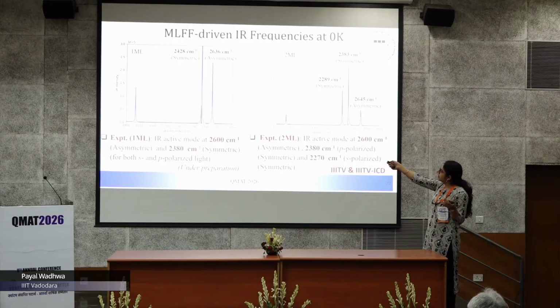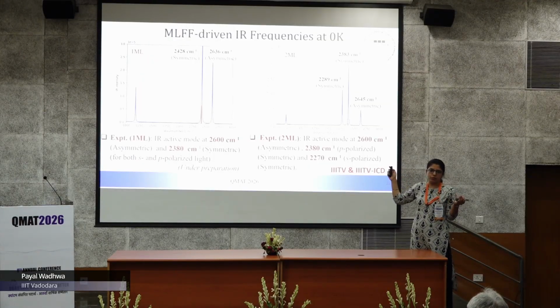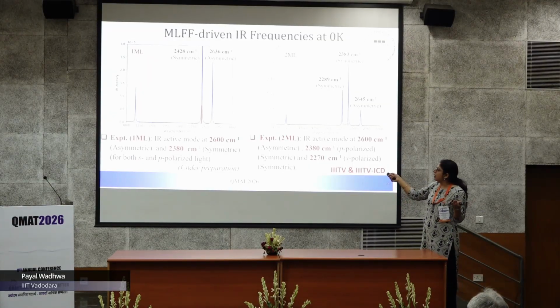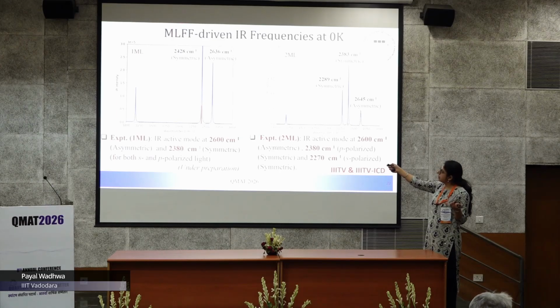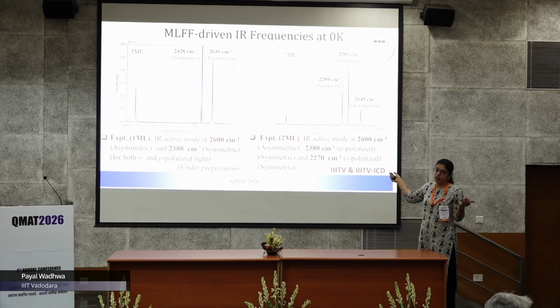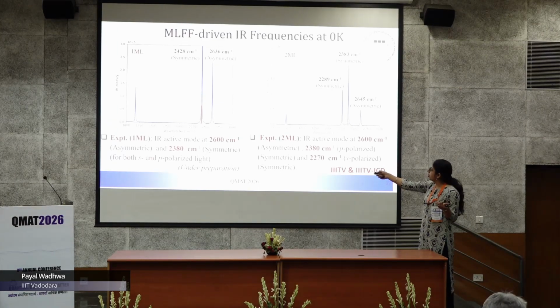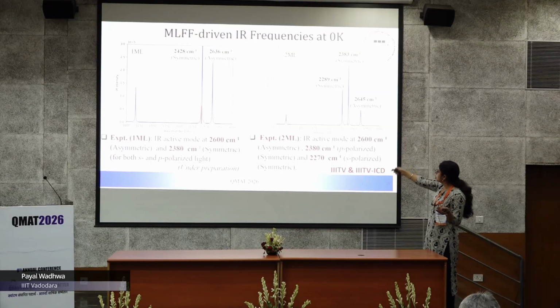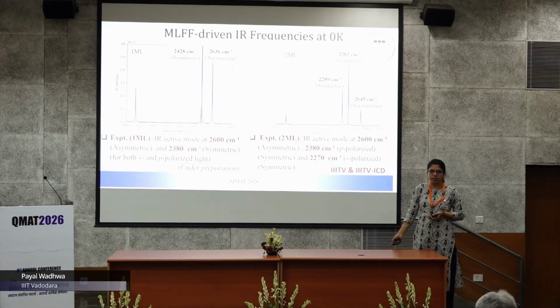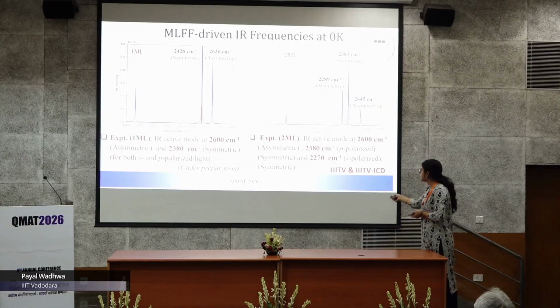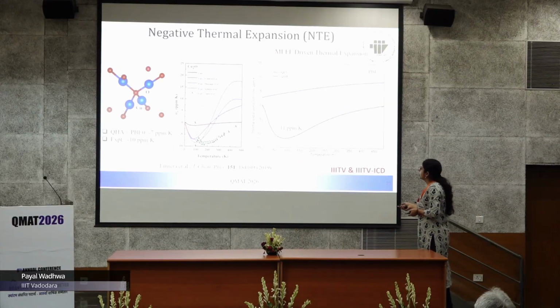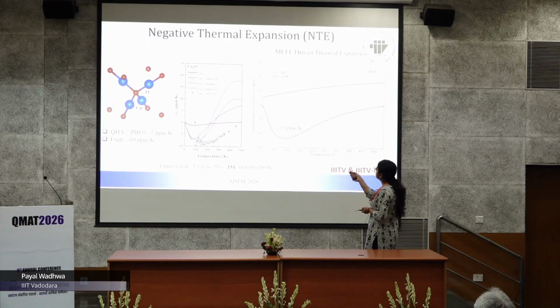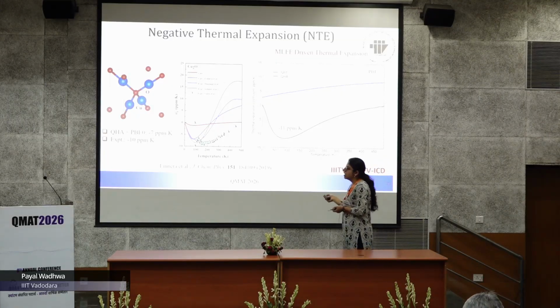For this IR, there is one flag in VASP, which you can easily find in the VASP wiki. From that you can determine MLFF driven IR frequencies, which is very quick actually. These values are also in good agreement with the experimental values, again indicating the robustness of the machine learned force fields. Another problem you can study is negative thermal expansion.